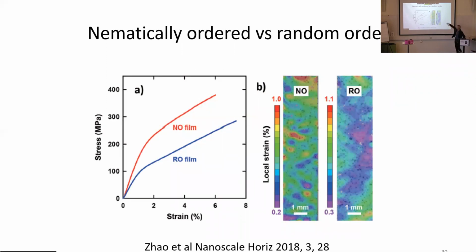And if you look at the deformation pattern, it's much more inhomogeneous for the random film and more homogeneous and with a stiffer behavior. But this, of course, is difficult to industrialize at the moment because it's a very slow process. But it shows us the potential. If we can do this in a rational way, if we can find applications where this makes sense, we can use this technology to further control the properties of the cellulose films.